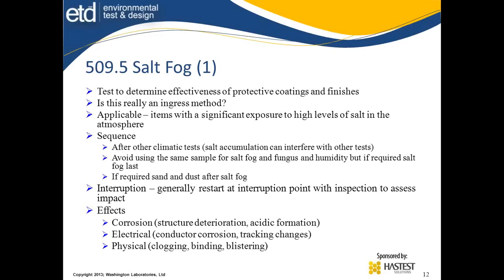The effects, obviously, the corrosion is the most obvious effect we see, the structural deterioration, acidic formation, things of this nature on the material as well as creeping into the material. The electrical, the corrosion of the conductors, the tracking changes on circuit boards and layouts, and salt getting into various articles and causing the arcing point between contacts, because it will accumulate and it will also hold moisture within it, so the electrical tends to get deteriorated. So if exposed, this takes a lot of cleanup to bring the unit back to a post-repair state.